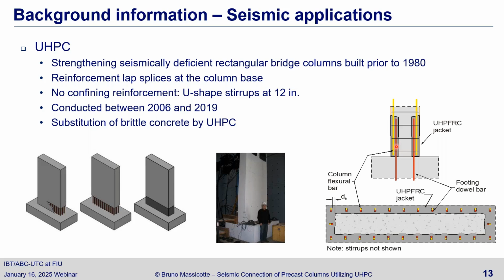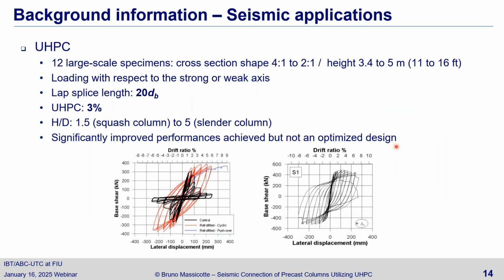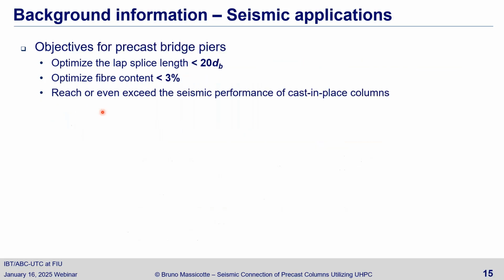And I got something. This is a control column in black here, and my first column in red. It was so good that I was not even able to break it because the actuator didn't have any stroke. And then in the coming years, I looked at the improvement given by UHPC on a lot of columns. However, in that project, I was using 20 bar diameter as lap splice length and 3% fiber content. So it was not optimized. So I thought, if it's working to fix a deficient existing column, could it be used for precast columns? So that was the idea.